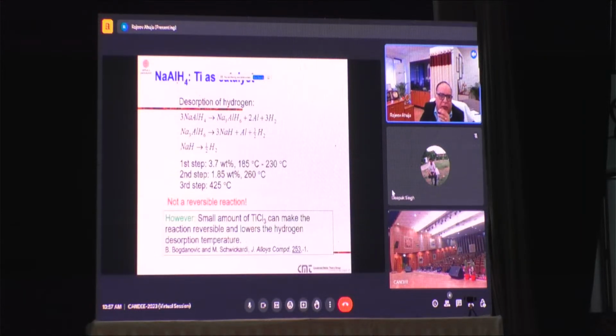If you take sodium alanate and look at the desorption of hydrogen, the hydrogen doesn't come out in a single step. It comes out of the system in three different steps. In the first step I get 3.7%, then 1.85%, and finally, in the last step, I get the total hydrogen out of the system. But if you look at the desorption temperature, it's very high.